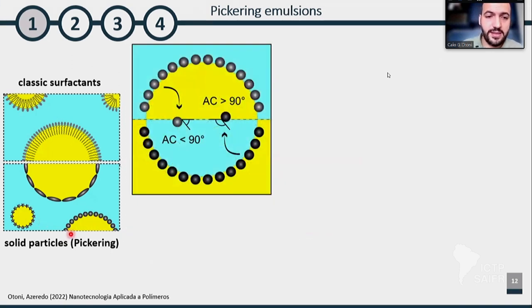This depends. For surfactants, we have the HLB number. For particles, which we call Pickering emulsions, it depends on the wettability of the particles. So depending on how the phases wet the particle, it will sit in the interface, because if it's too hydrophilic, it will go to the water phase. If it's too hydrophobic, it will go to the organic phase. So it should have an intermediate wettability for it to sit in the interface, right?